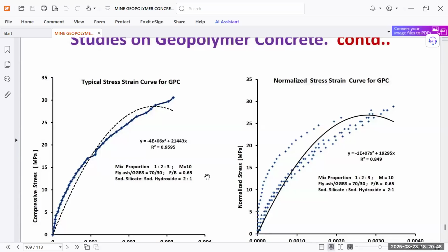For different molarity you can get different results, with a fly ash to GGBS ratio of 70 to 30, and a fluid to binder ratio of 0.65. Sodium silicate to sodium hydroxide is in the ratio 2 to 1. For this we made the test stress-strain curve. You can see it is similar to concrete. So by this, we can see that it is also getting the required results as per normal concrete.